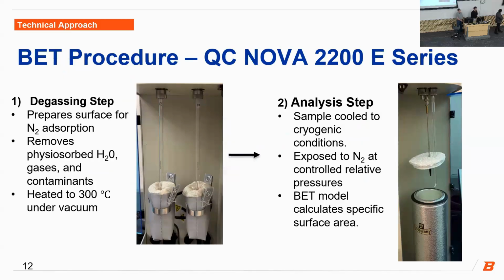Taking a closer look at the BET procedure, the machine we used for this was the Quantachrome Nova 2200E series, and it consists of two main operational steps. The first is the degassing step. This prepares the surface for nitrogen adsorption. You put the sample in the test cell and into the heating mantle, and then you heat it up to 300 degrees Celsius under vacuum. This is going to remove physisorbed water, gases, and any other contaminants in the system.